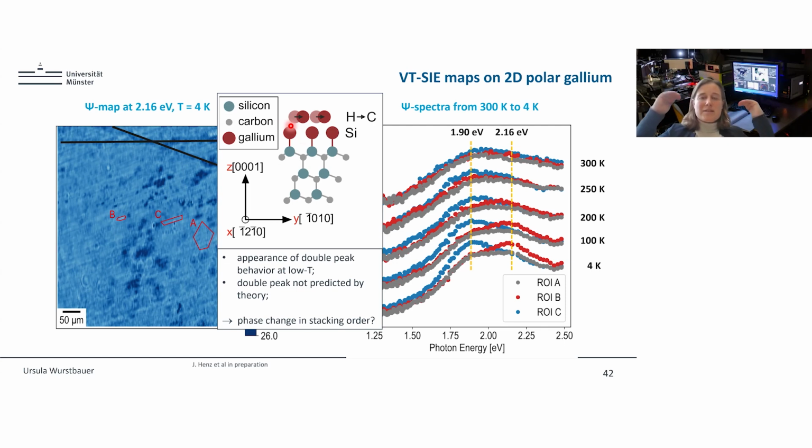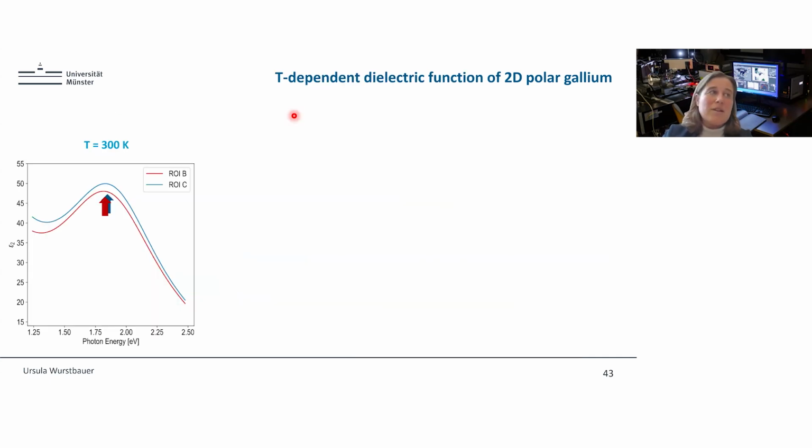And if we condense it down, depending really on the energetics on the interface, some of the material can overcome the energy barrier and then sit in the stable, low temperature phase, or the ground state. And another part is still sitting on these metastable higher energy states, which would explain the behavior. And that's now the confirmation of this idea.